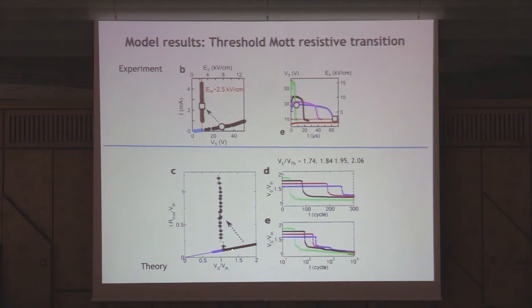You see systematic behavior of this: you increase the voltage over the threshold, and you see that the transition goes faster and faster. So this is a linear scale, and this is a log scale that lets you see that this thing really is very rapidly increasing. Since this is a simulation, we can ask about all the details of how this happens.